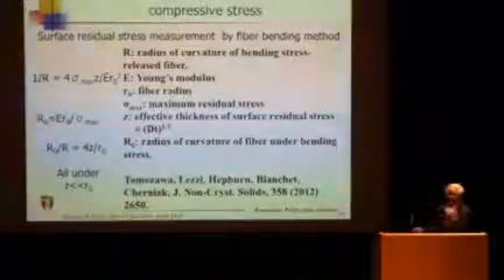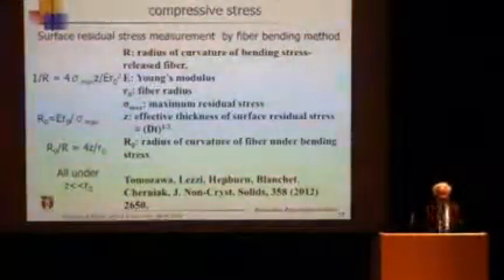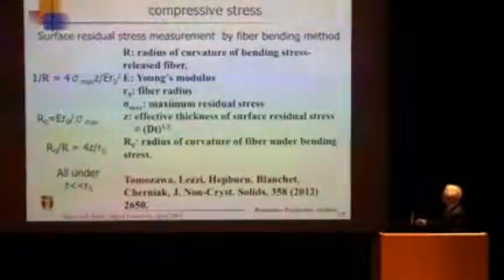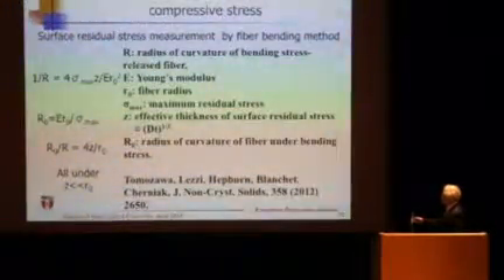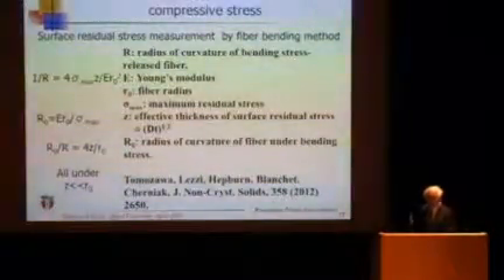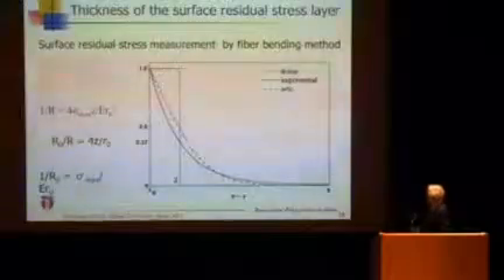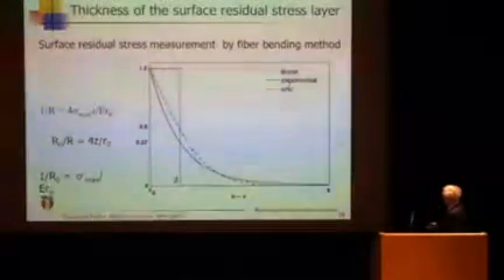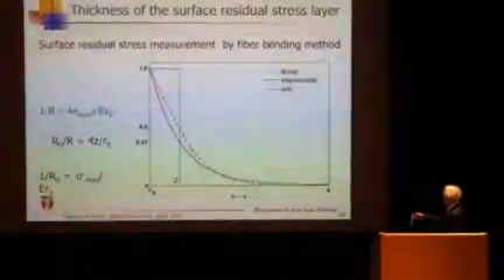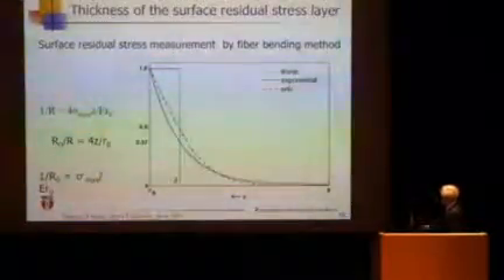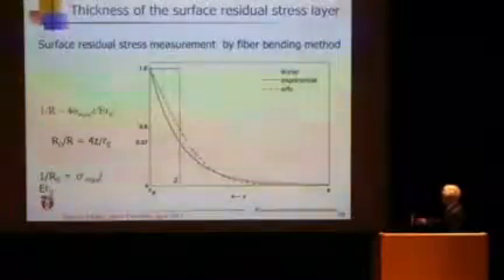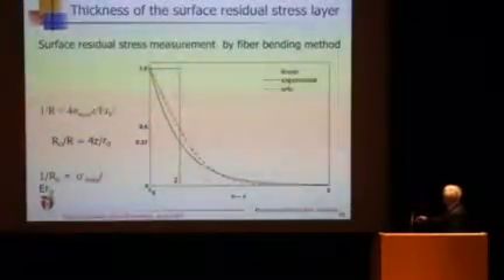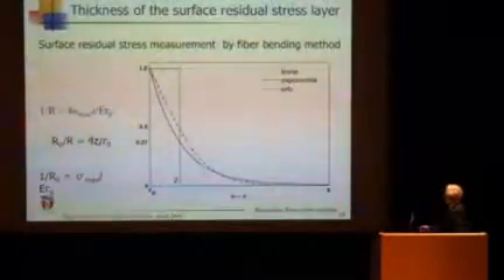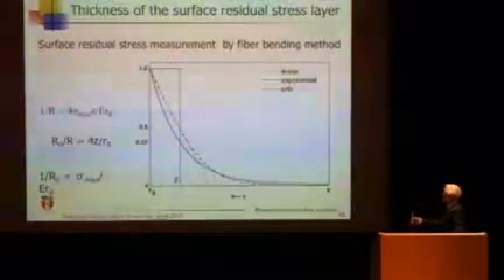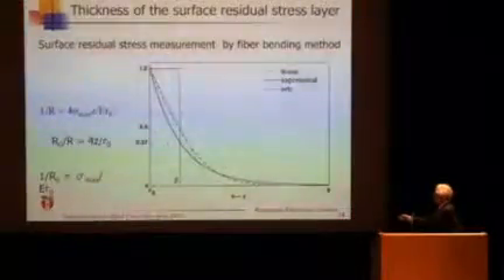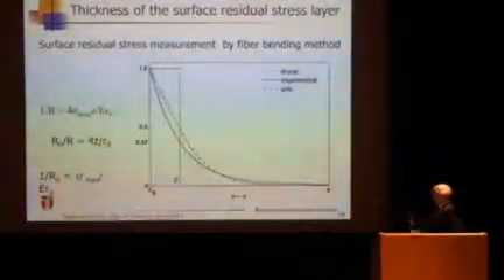And the kinetics of how quickly the bend happens depends upon how much surface relaxation is happening. So we assume that the surface radius of curvature is changing, and the relaxation is happening to the thickness Z. If you have a cross-section of optical fiber, this is half of the cross-section, and the surface layer is relaxing. We want a simple assumption: step function relaxation, or exponential relaxation, or if it's diffusion, complementary error function relaxation, or straight coming down. We tried many different profiles, since we don't know for sure, but the equation was almost always the same, so this type of expression can be used. The radius of curvature is determined by how much residual stress and how much depth of relaxation happens.